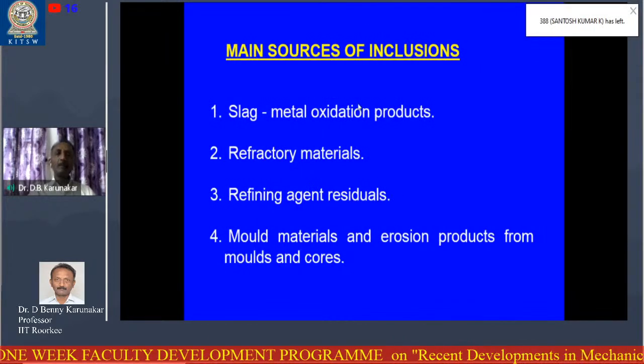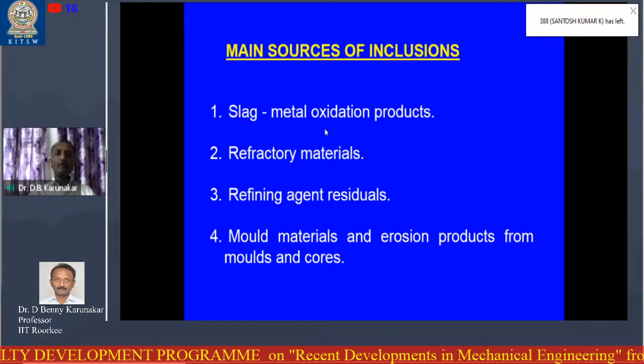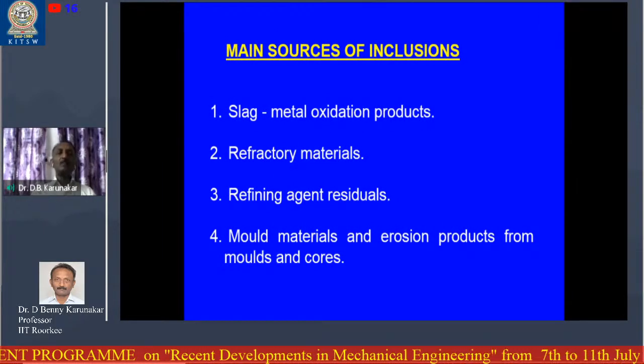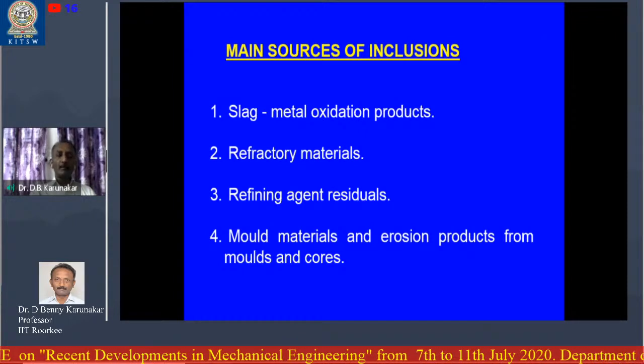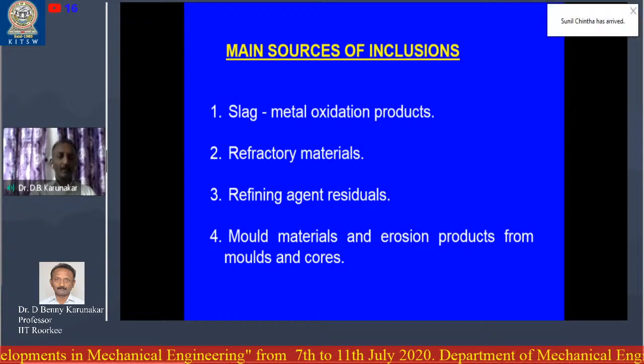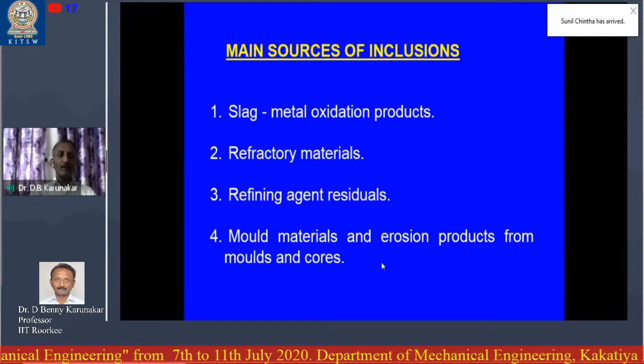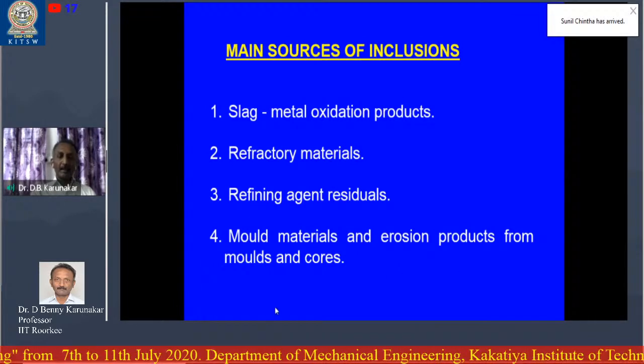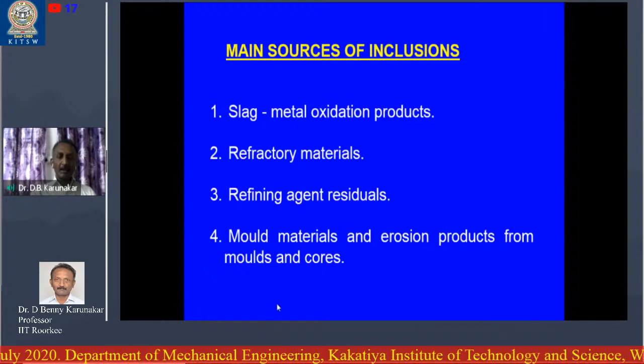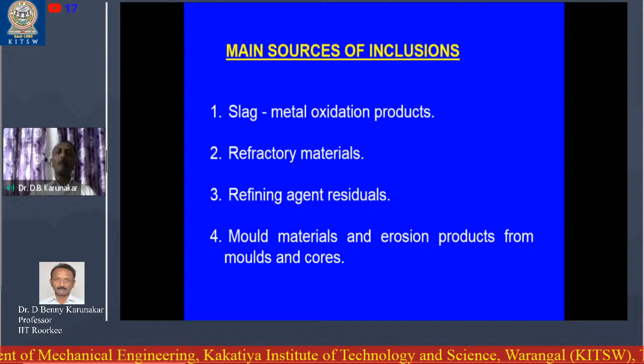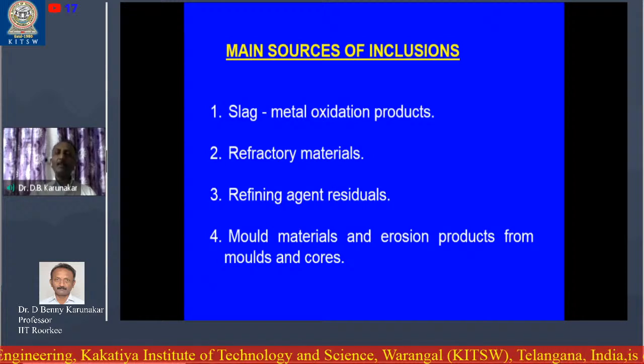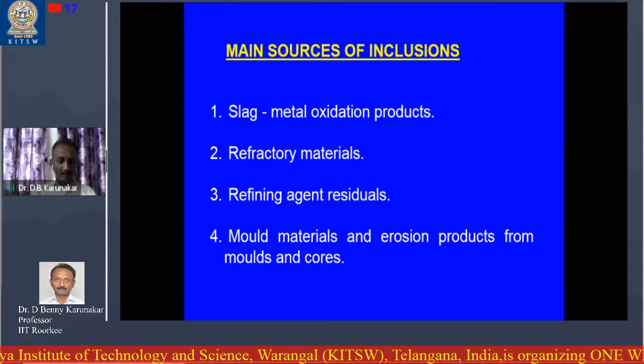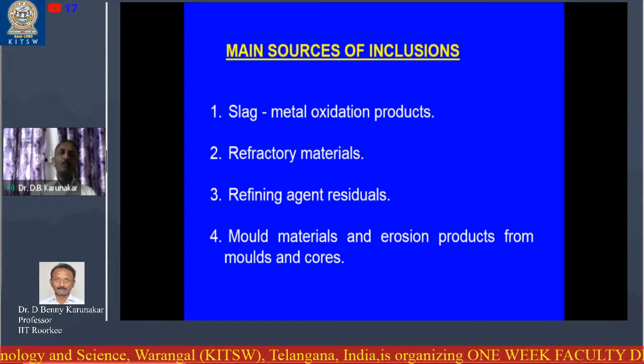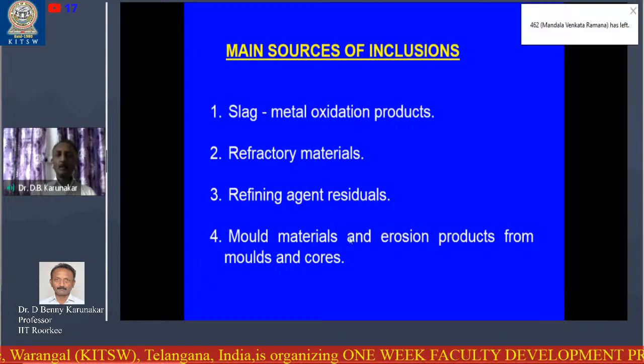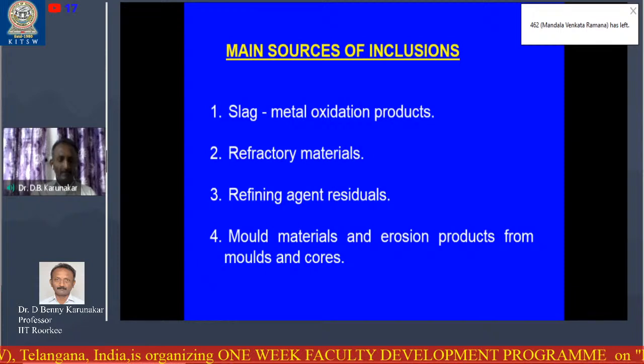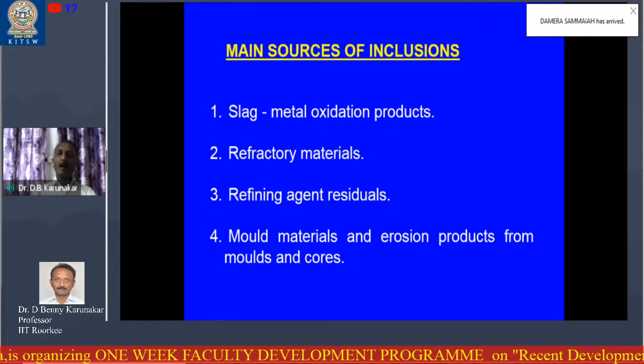What are the main sources of inclusion? Slag, metal oxidation products, refractory materials, refining agent residues, molding materials, and erosion products of the mold. They all come along with the mold and are deposited somewhere on the surface of the casting. These are known as the inclusion. Certainly these cannot be accepted on the surface of the casting or inside the casting.